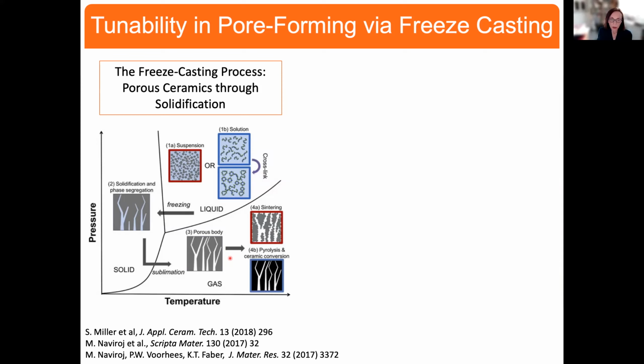solvent. We generally have to go through one more step, and that is if we had a powder, we would sinter it or fuse those ceramic powders together to form a robust solid. But again, that pore network is maintained, as you see here, that we have created through the freezing. And alternatively, if we're working with a pre-ceramic polymer, we pyrolyze this. So we end up with a generally very lightweight and porous solid that has some degree of robustness because of this final step.